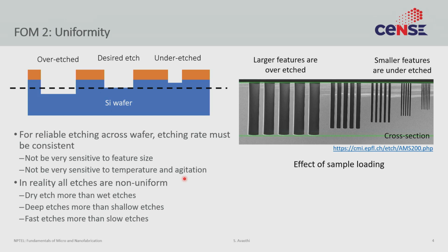If you remember that during CVD we talked about diffusion through a boundary layer of how etchant needs to get in, the precursor needs to get in and the byproducts must get out. Something very similar happens even when you do etching. In this case, the etchant must get in and the byproducts must get out. And if it's just a static solution, then you are just depending on diffusion to do this process, but that can sometimes be non-ideal.